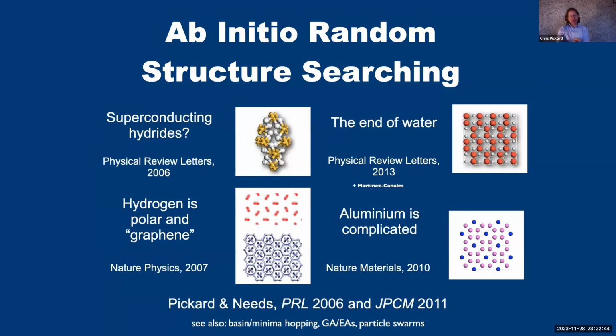But following that, we went on to explore the high pressure phases of hydrogen. And in fact, most of the theoretical candidate structures for hydrogen under pressure have been derived by AIRSS-style calculations. And indeed, some of our phases are now the best models that experimentalists have for hydrogen at high pressure, in particular phase 3 and various forms of phase 4. We also went on to explore the behavior of the hydrogen-oxygen system at high pressure, and found that at very high pressures, the H2O composition was not stable.